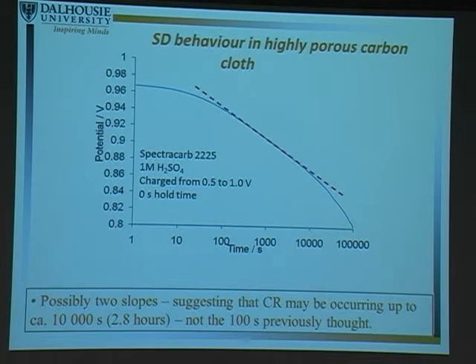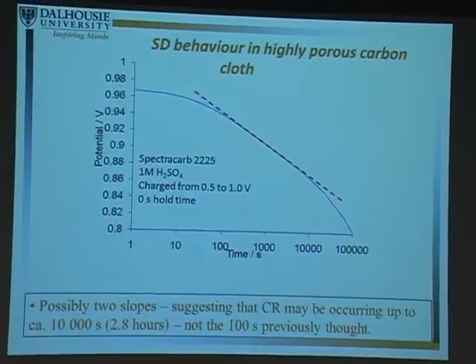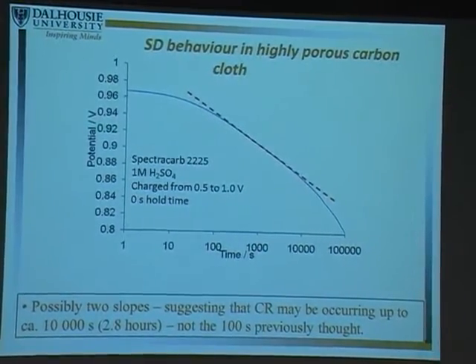The key thing here is that this takes 10,000 seconds for this carbon. And up to this point, everybody believed the charge redistribution would end within about 100 seconds. 100 seconds was sort of the longest time anybody expected this to happen. And so what we're now seeing is that charge redistribution is a significant effect, and it takes long periods of time before it stops.